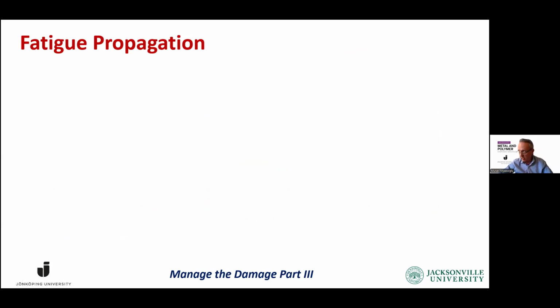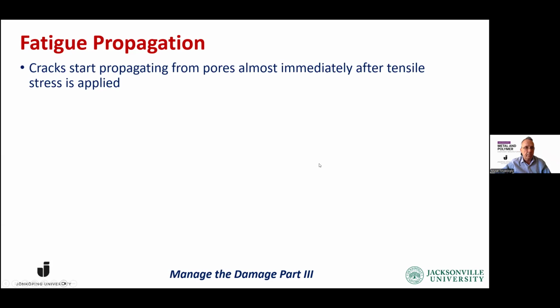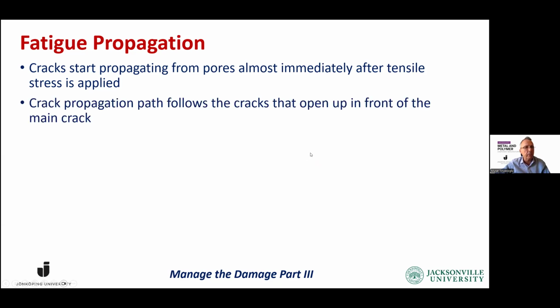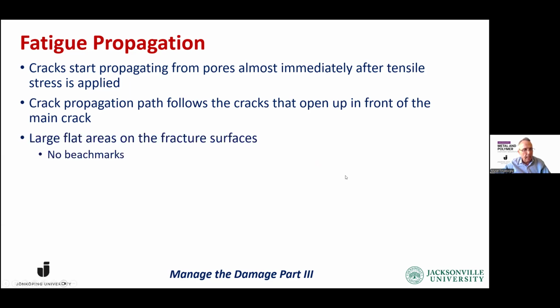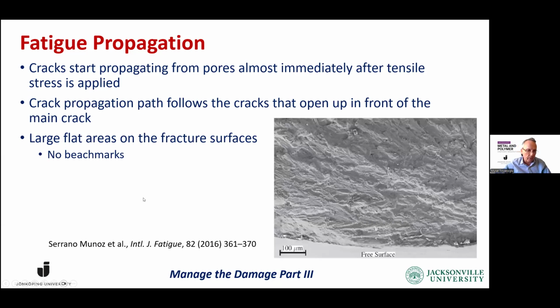So that's different from the crack propagation that we've been taught. These are all small cracks that opened up and that finally joined forces to form the long crack. So it's all small cracks, not a big long crack that got initiated from a single point. There are multiple crack initiating sites. Obviously, these are bifilms that start immediately with almost no threshold. And that's obviously small crack propagation, and the crack propagation follows the cracks that open up in front of the main crack. So small cracks join forces to become the main crack. And there are also large flat areas on the fracture surfaces without any beach marks that were reported, like this one. That's a clear indication of a bifilm.